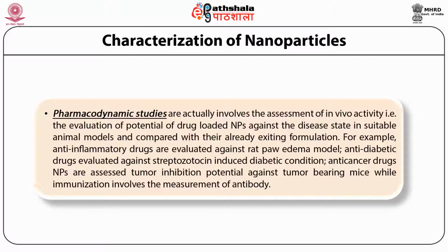Another example includes Sina et al. In 2013 they developed polylactide co-glycolide nanoparticles containing voriconazole by multiple emulsification process and also made them porous by presence of an effervescent mixture for better pulmonary delivery. Pulmonary deposition of the nanoparticles was analyzed by customized inhalation chamber. The drug was found in lungs for 7 days in case of porous and for 5 days in case of non-porous after administration. Nanoparticles with enhanced drug loading were delivered to murine lungs.